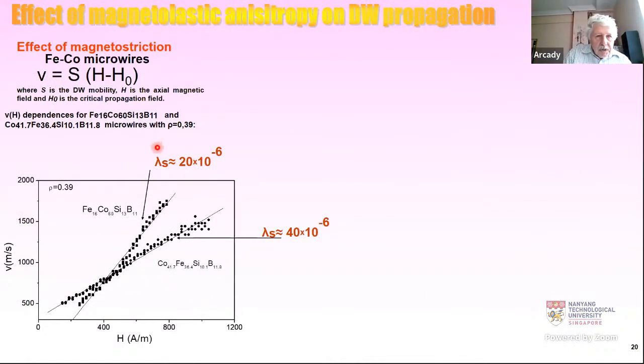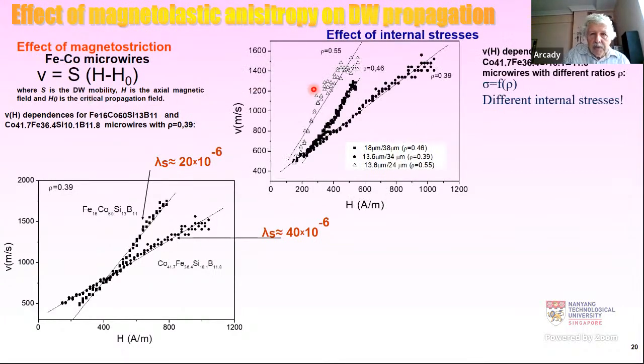So, for example, here we choose two different compositions of different magnetostriction, and the same ratio. So we fix the geometry of the samples. What we see is that in both cases the velocity versus magnetic field presents a linear dependence, but the slope is different, and the slope of this magnetic field dependence is given by this relationship, where S is the domain wall mobility. So domain wall mobility can be tuned by magnetostriction in this case, so by magnetoelastic energy.